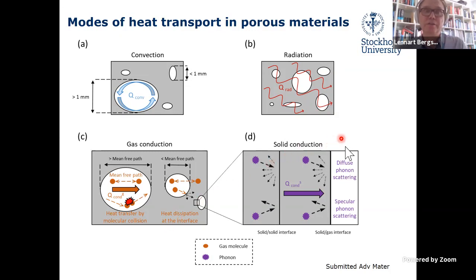The solid conduction is all about phonon transport, lattice vibrations. If you can then scatter these phonons, you can also reduce solid conduction. So interfaces play a major role here - scattering at interfaces, which can be interfaces within the material, grain boundaries, but also interfaces between different components, in particular if they are nano-sized.